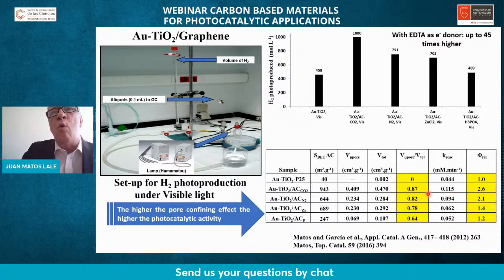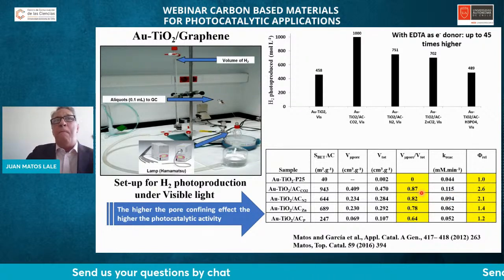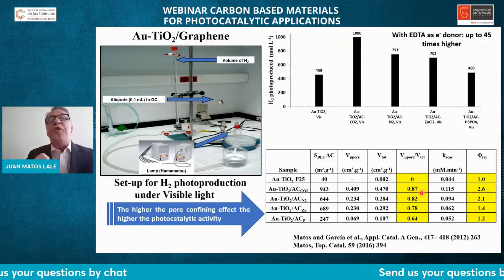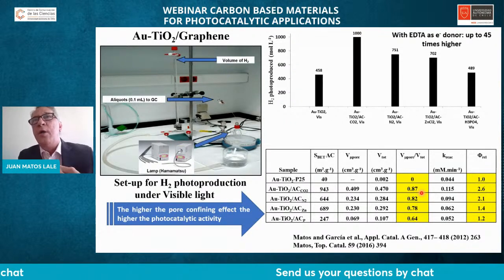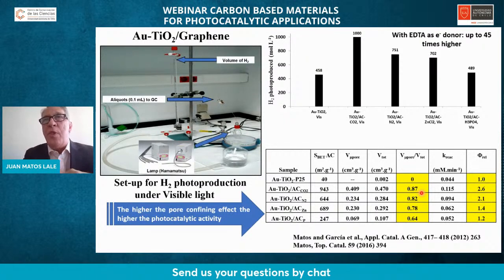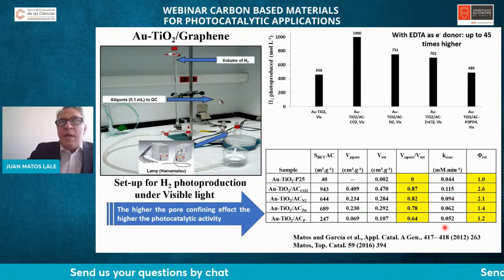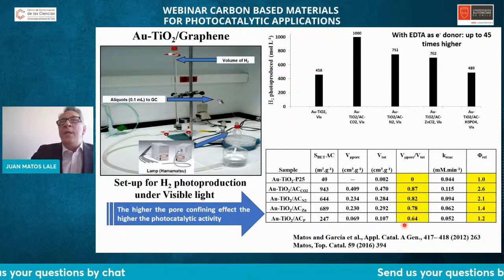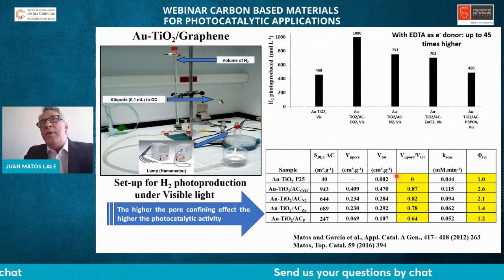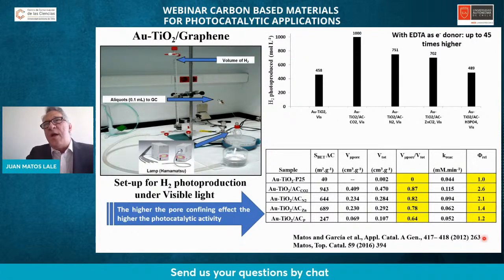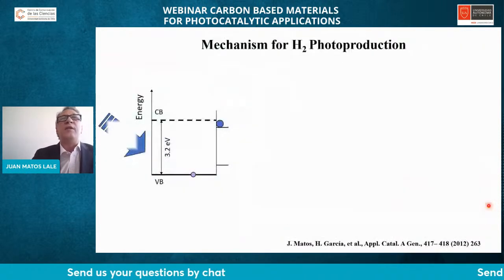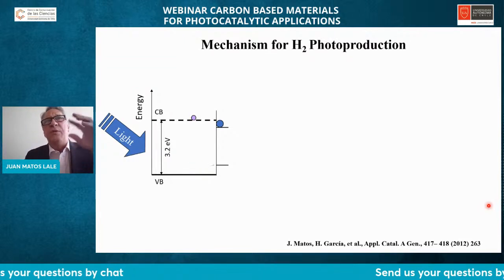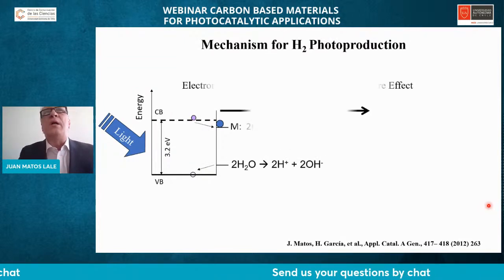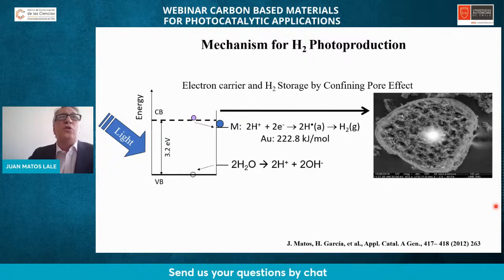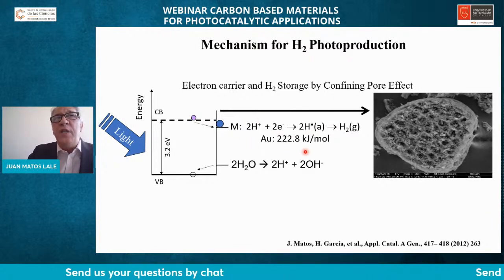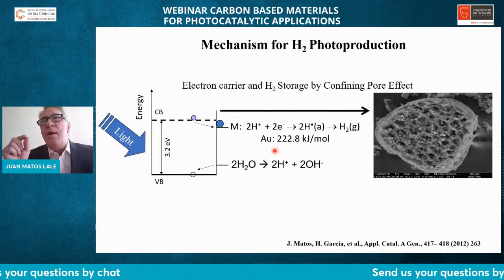The higher the quantity of nanoporous material, the more important is the pore confining effect within the pores of the support, in this case, nanoporous carbon. And you can see that there is a great relationship between the ratio that measures the pore confining effect and the quantum and the relative quantum efficiency. And we propose a modification of the classical mechanism of the hydrogen photoproduction in terms of the electron affinity of gold, which was our catalyst.